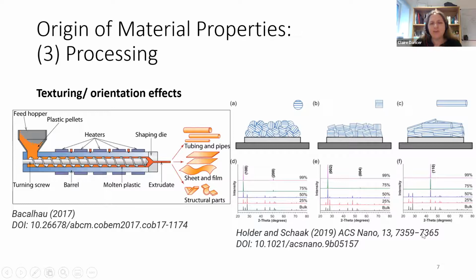The second place where we see texture and orientation is typically in structures like these. This paper is quite an interesting paper. Actually, it's on detecting preferential orientation in X-ray diffraction. It's a very nice paper if you're looking for a starter guide on that kind of thing. What it basically shows is that depending on the type of particles we're dealing with, if we're depositing thin films, we can get a strong degree of preferential crystallographic texture, and that can be detected then by XRD.